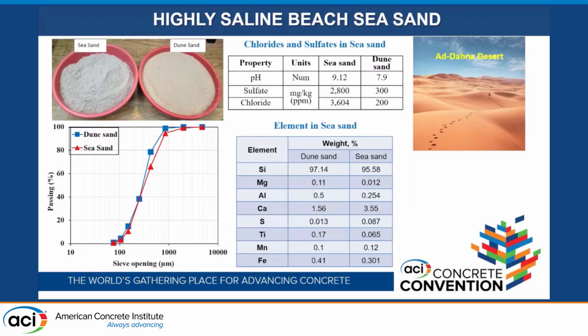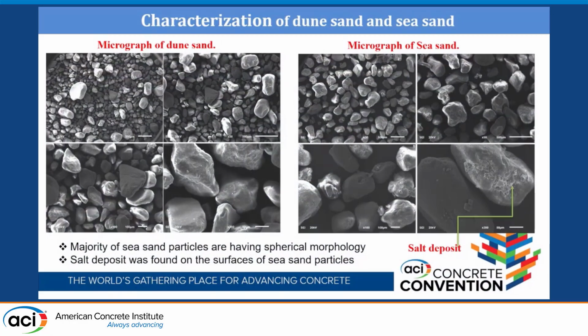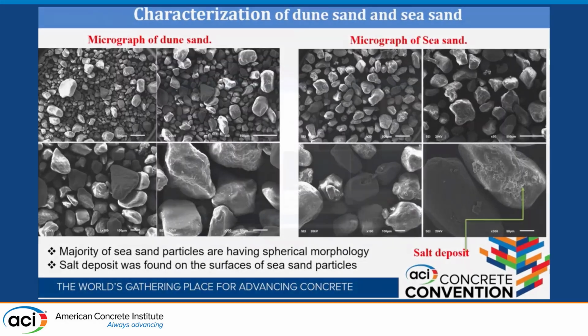Not only that, we also took the sea sand from this area, which is also very highly saline, most probably because of the high salinity of the seawater. You can see that the normal sea sand, or coastal sand, which was collected had 2,800 sulfate and 3,604 chloride, as compared to the dune sand from the Ad-Dahna Desert on the right, which is about 300 and 200. So there is a very high content of chloride and sulfate in the beach sea sand used in our research with Aramco. The characterization of the sea sand also showed salt deposits on the surface of the sea sand particles.